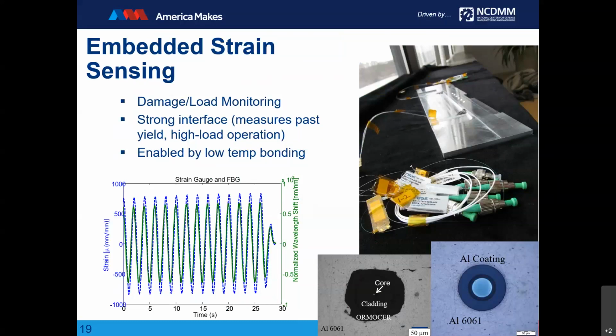The pictures at the bottom right actually show the embedding. The picture at the far right is a coated fiber. So we took a ceramic fiber and it was coated in aluminum by a third party, and then we embedded that. And you can see that the matrix of the print job flowed around that fiber, fully encapsulating it. Like I said before, this would be fully embedded, and we can share strain or transfer strain from the matrix to the fiber. The picture on the left there is actually a plastic coated fiber.